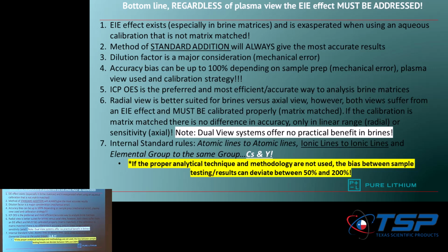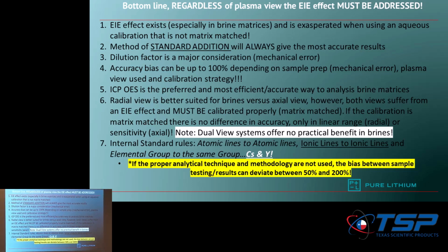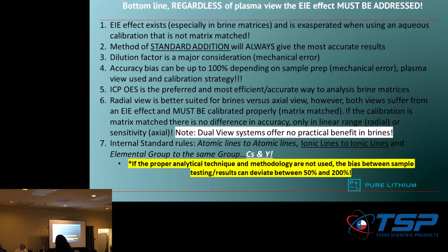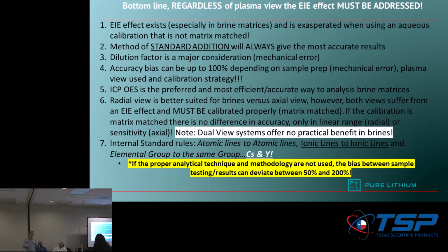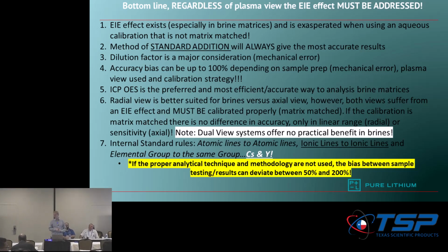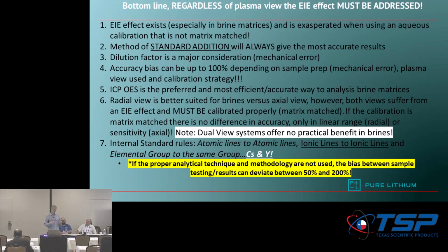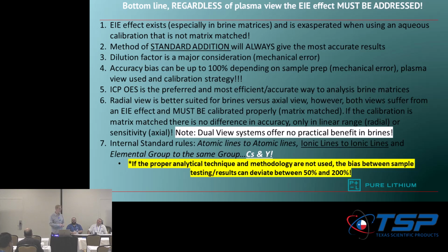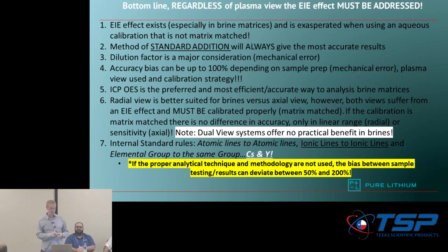So the bottom line is, if you want to get the most accurate, precise results, there's no substitute for a method of standard addition. It's a lot of work. A lot of people don't want to do it, but if you have enough material, you split it into 4 or 5 aliquots and you start spiking it, it will back calculate the concentration in it, it will eliminate your matrix effects, and it will give you absolutely the best precision and accuracy. Unfortunately, some of us have to follow regulatory QC procedures, and some methodology does not consider standard addition the right way to do things. So a matrix match as best you can.